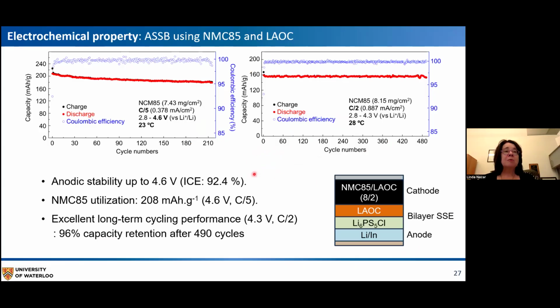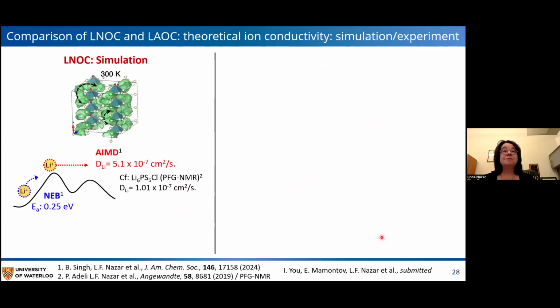So again, very promising cycling stability for these materials. This shows the data at up to 4.6 volts, where we see some fading, whereas at 4.3, we really see remarkably stable performance. This is under pressure, but it's at close to room temperature. And the utilization is very good. In this case, up to 200, it's about 208 milliamp hours per gram, and a very stable system. We use argyrodite as our interface because LAOC, like the halides, is not stable to reduction.